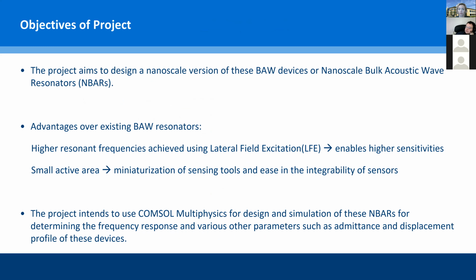So as I discussed, the major objective of this project is to miniaturize these existing bulk acoustic wave resonators, and what we propose is a nanoscale version of these thin film bulk acoustic resonators. To achieve this, we used lateral field excitation. As you saw in the previous picture, there is a top electrode and bottom electrode, and a piezoelectric transducing unit sandwiched between them. But in this project, as you will see in the coming slides, we have used lateral field excitation with a coplanar electrode arrangement, which would excite the transducing layer laterally and not longitudinally, which would enable us to go for thin films. By thin films, I mean films in the range of nanoscale.